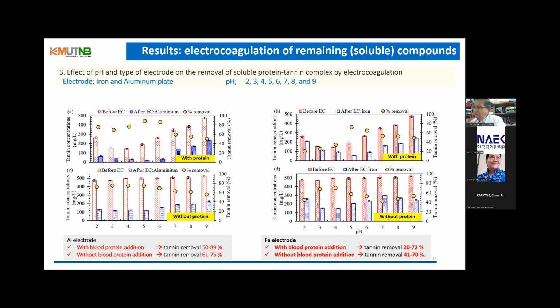The tannin removal was significantly higher for the electrocoagulation with the addition of protein than without, in the picture below. When using iron electrode, the tannin removal reached 72%. Similarly, the tannin removal was significantly higher for the system with the addition of protein. Electrocoagulation with aluminum electrode results in higher tannin removal than iron electrode because the formation of protein tannin complex is favored at acidic pH, whereas the formation of iron hydroxide complex is favored at alkali pH. In addition, aluminum hydroxide complex exists in various forms with more definite binding sites when compared to iron hydroxide complex.